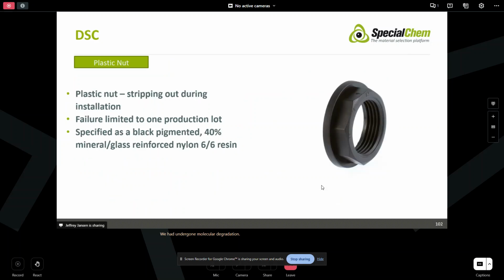Here we have a plastic nut. It's stripped out during installation. The failure was limited to one particular production lot. This was specified to be a black pigmented 40% glass and mineral reinforced nylon 6,6 resin.